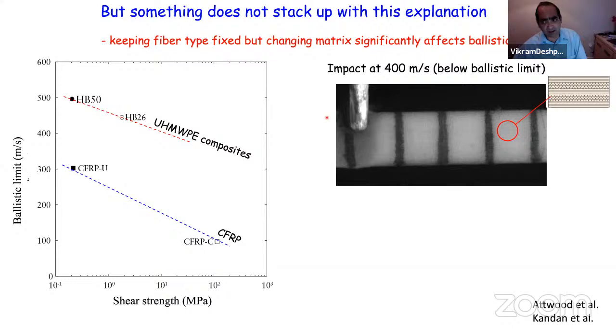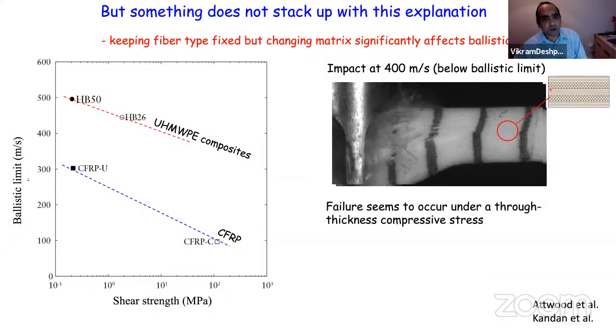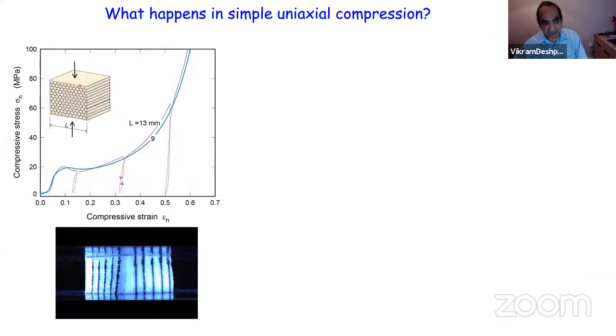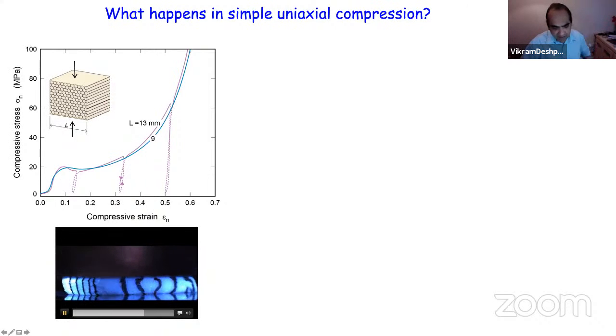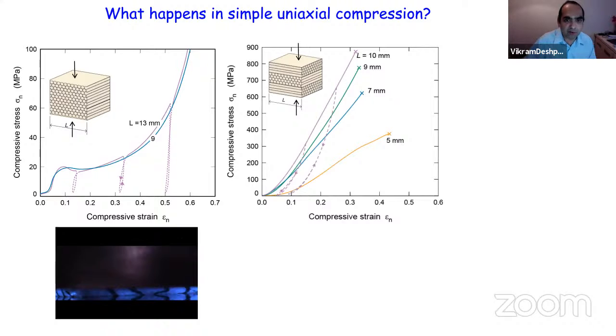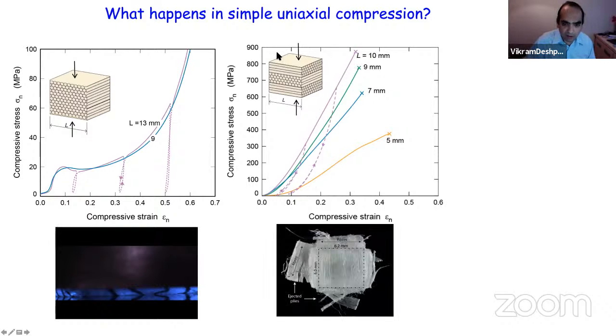And so let's try to understand why that is the case. Why would you get failure when you compress this composite under uniaxial compression in this way? So if you do that experiment and you take a UD composite, normally these composites are 0/90 composites, but we don't do that. We just make a unidirectional composite and we compress it. And this is what will happen. It just compresses that way, and that's it. No failure at all. But if you now make it into a 0/90 composite and you compress it, something completely different happens. You get enormous strength, and then it just bursts. It just completely explodes, and you don't get this kind of ductile behavior that you saw here.